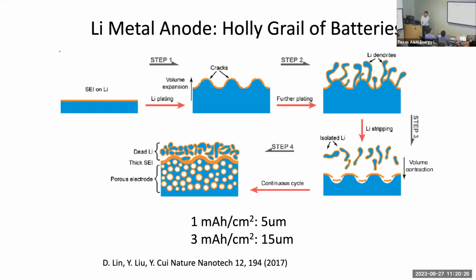Actually, most battery fires are due to dendrite plating. Even if you don't use metallic lithium as the anode and you use graphite, with time, when you use your battery over and over, this starts to happen, particularly under fast charging conditions. Once you strip lithium, you might strip from the bottom of this dendrite, causing isolated lithium formation. You are losing metallic lithium. You lose your capacity very fast, and before long, your battery will die.